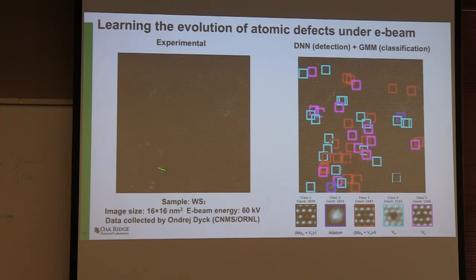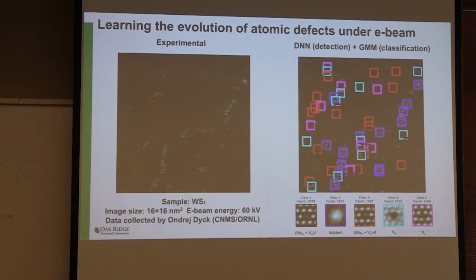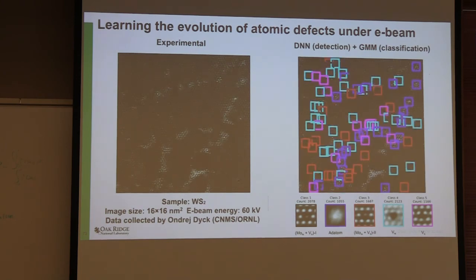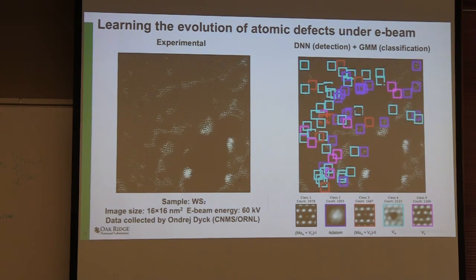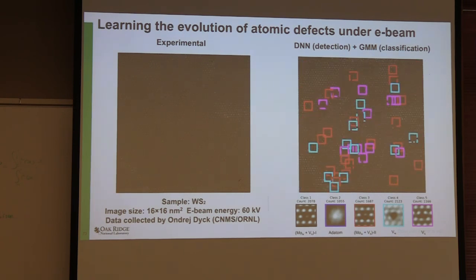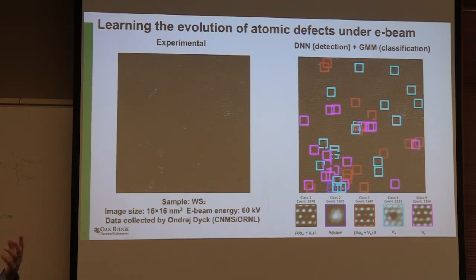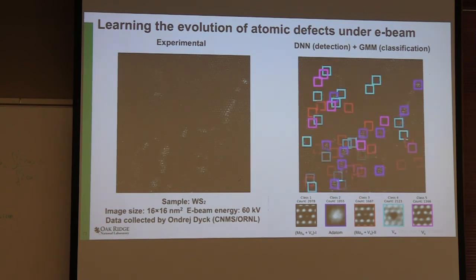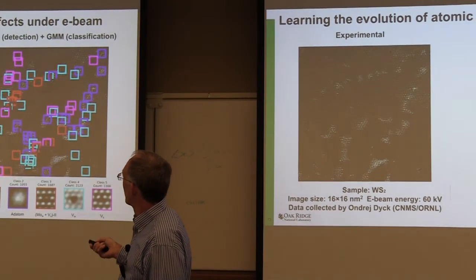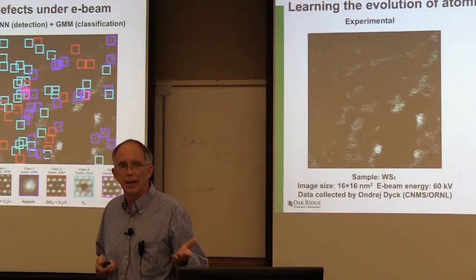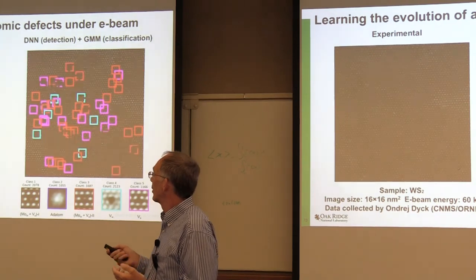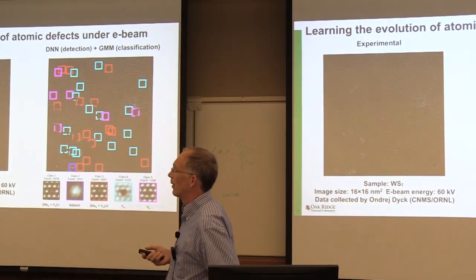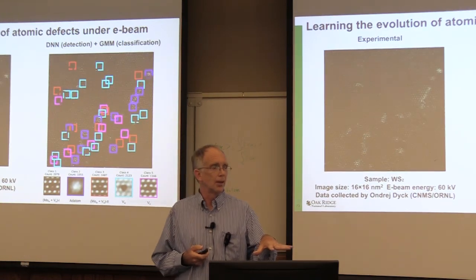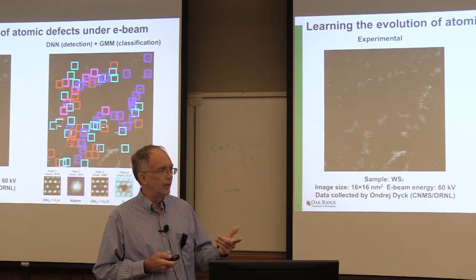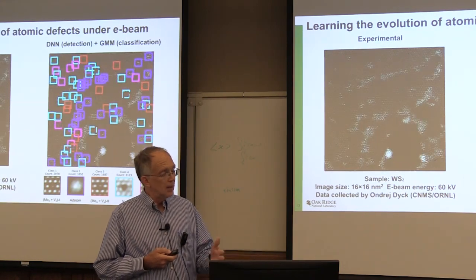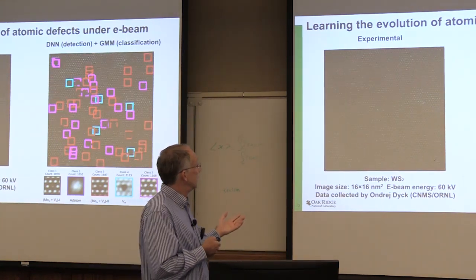So this is an example of what we can do. Again, our favorite layer of material. This one is tungsten disulfide, it turns out, that has been doped with molybdenum. So the tungsten is going to be brighter and the molybdenum is less bright. And we can train that neural network to detect any defect in the system that is caused by just shining the electron beam on it. Because like I mentioned, if you focus the electron beam too long, you'll knock atoms out and then atoms will move. And that's a defect. And you can train this neural network by just using a set point. A perfect crystalline lattice is what it should look like, and any breaking of that symmetry will be a defect. So that's what the neural network basically learns, is symmetry breaking in a lattice.